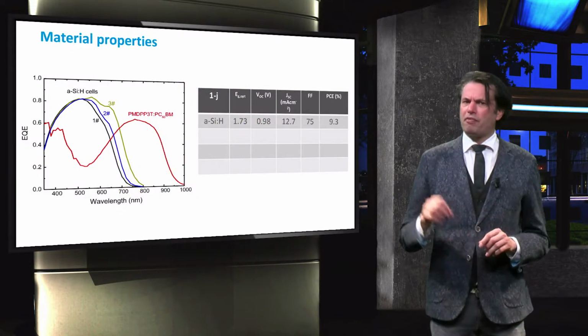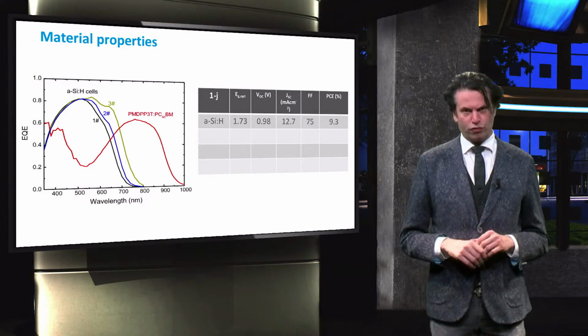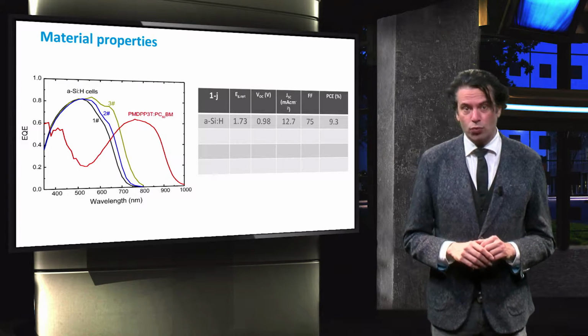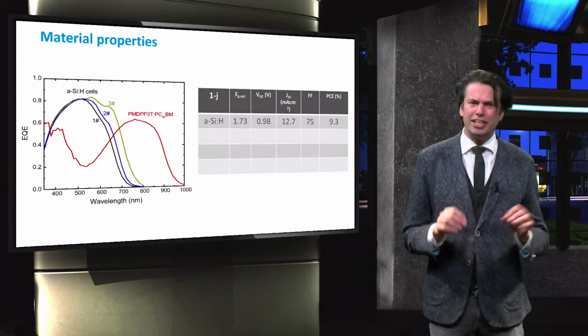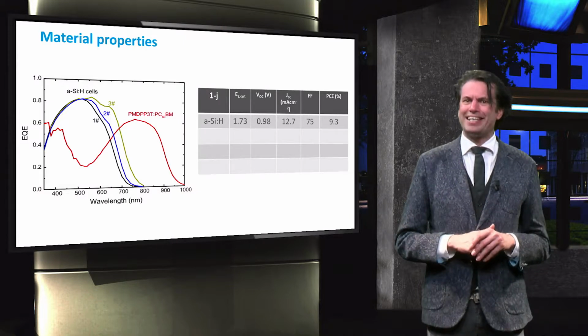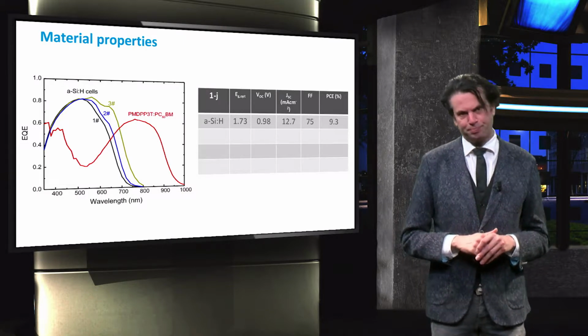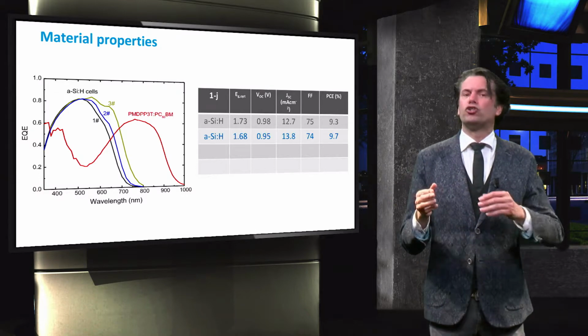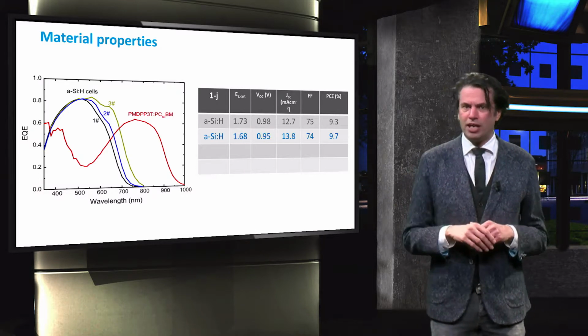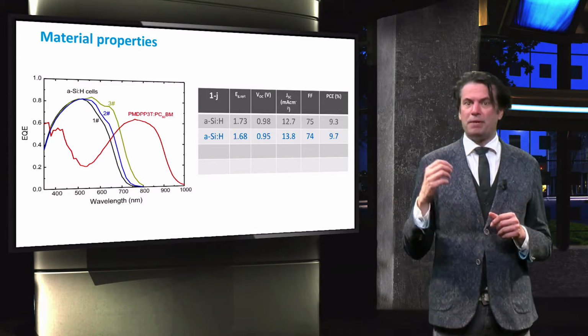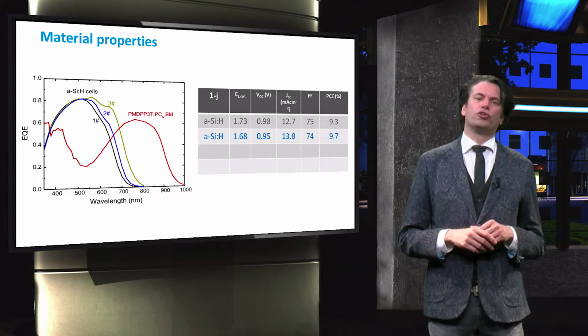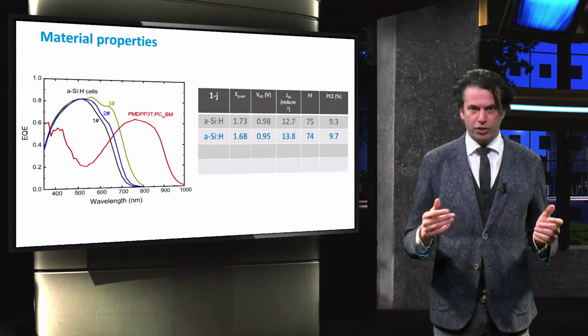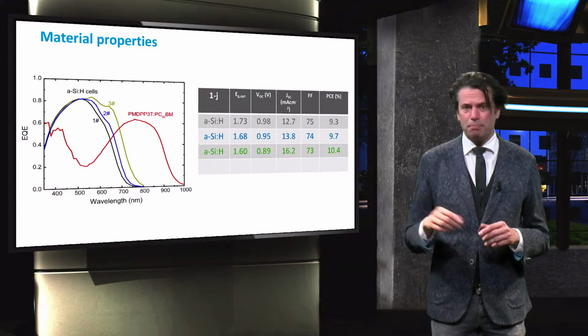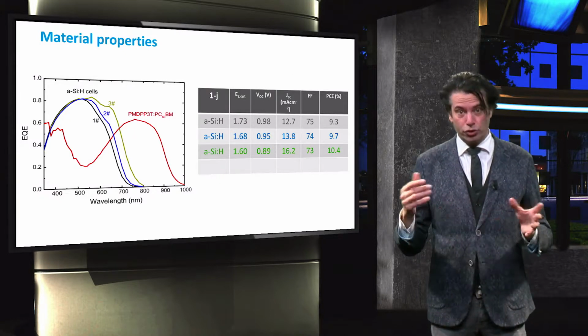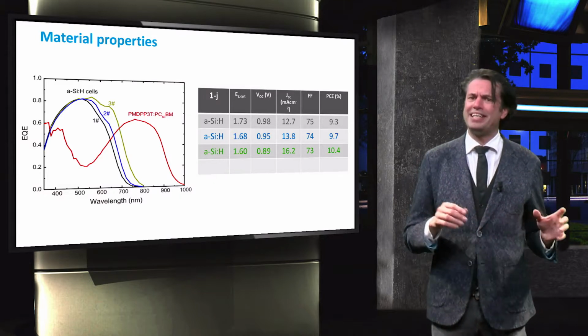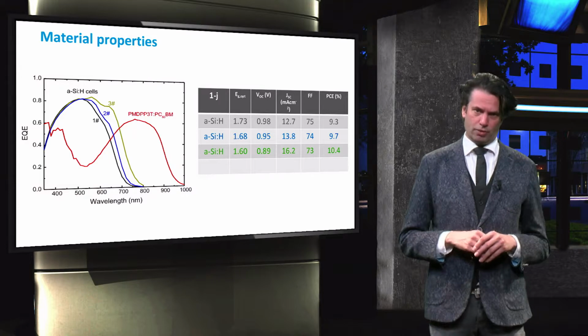For these experiments, three different types of amorphous silicon have been chosen. First, a high bandgap amorphous silicon with a bandgap of 1.73 electron volt, leading to an open circuit voltage of 0.98 volts in a single junction solar cell. Secondly, an amorphous silicon with a smaller bandgap of 1.68 electron volt, which, if integrated in a single junction PIN solar cell, leads to an open circuit voltage of 0.95 volts. Thirdly, an amorphous silicon material with the lowest bandgap of all three, being 1.6 electron volt, which results in an open circuit voltage of only 0.89 volts in a single junction solar cell.